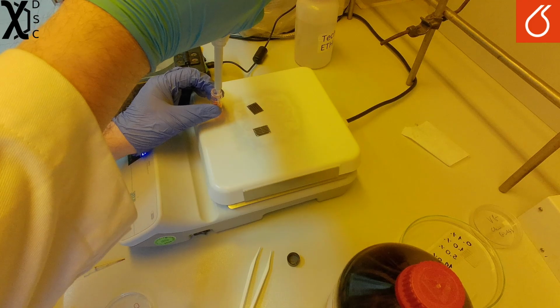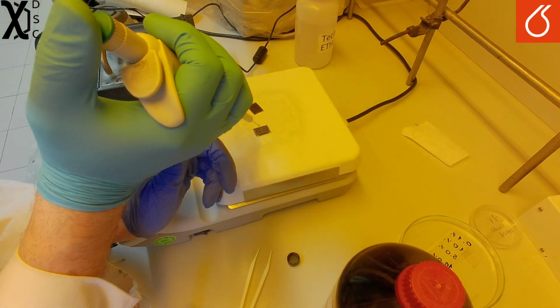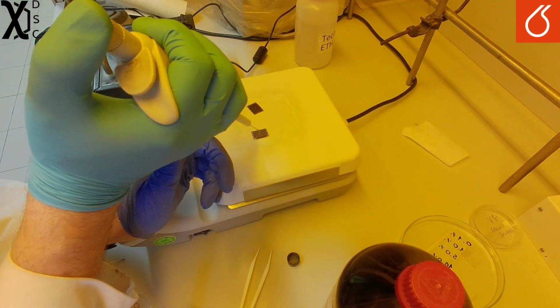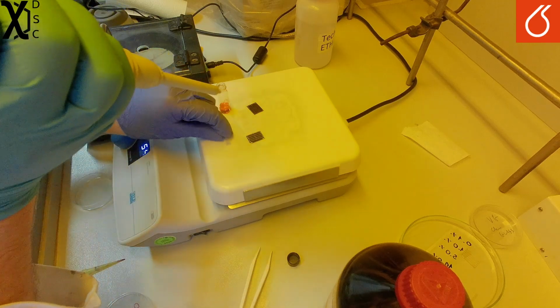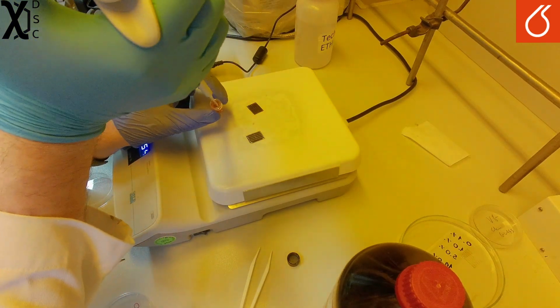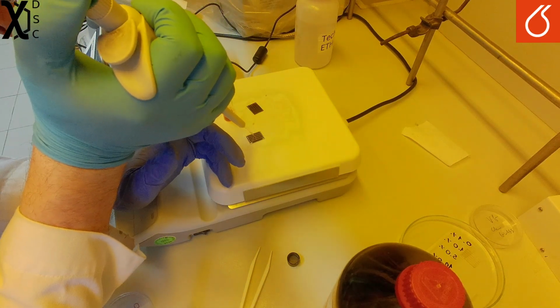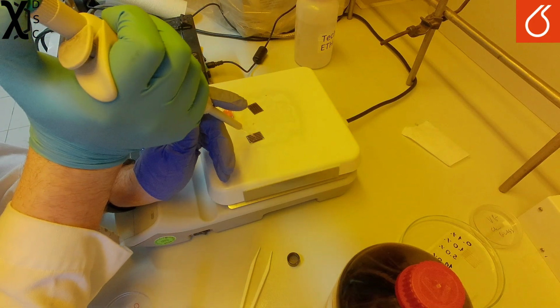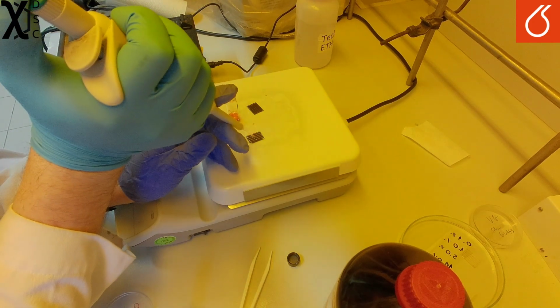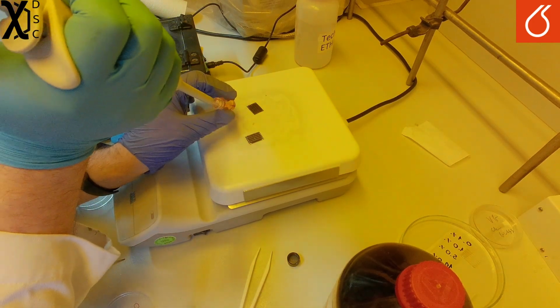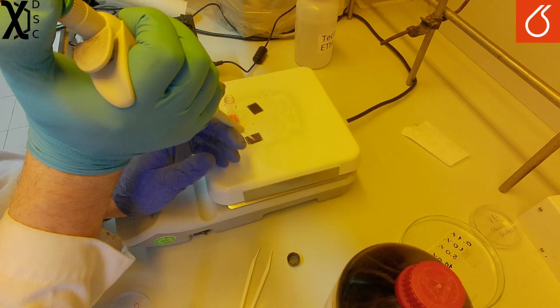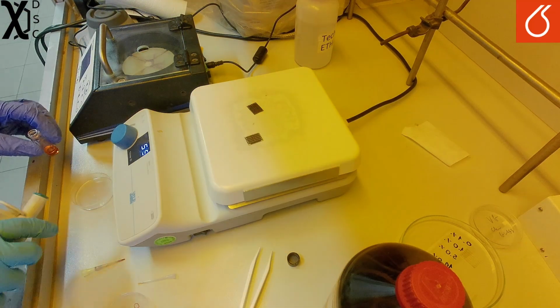First, I will show drop cast film coating. In order to do this, a small amount of compound is dropped onto the gate section of each substrate. The compound may be optionally heated during this step. Subsequent to it, the substrate is often annealed. In this example, I have used 1 microliter of 0.5 mg per ml P3HT in a 1:4 mix of chloroform and orthodichlorobenzene, heated to 50 degrees Celsius. The resulting film, as imaged under a microscope, is shown here.